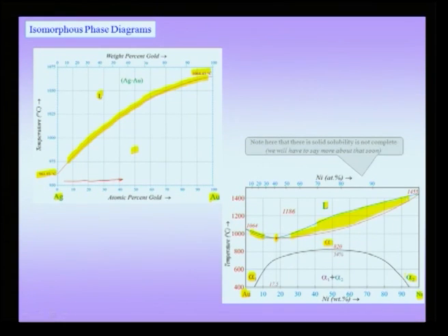That is why we are able to go from this end of the phase diagram to that end by constantly increasing the percentage of nickel. But between the two, alpha 1 and alpha 2, if you notice here carefully, you find that there is a two phase mixture region below a temperature of about 820 degrees Celsius, and the maxima of this curve lies at 54% of nickel. So, if I am below this maxima and I intersect this, that means suppose I am cooling an alloy with 40% nickel, I will first start off with being a liquid, then I will go into the two phase region where I will have a liquid plus alpha coexisting.